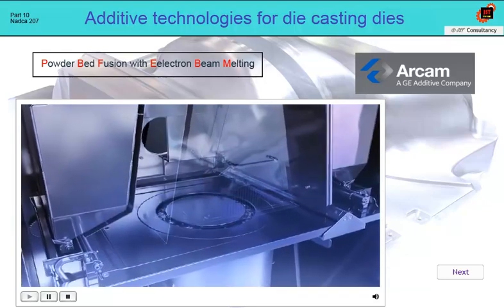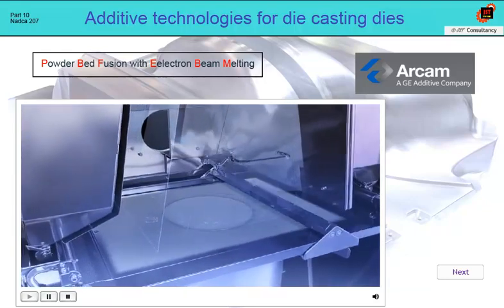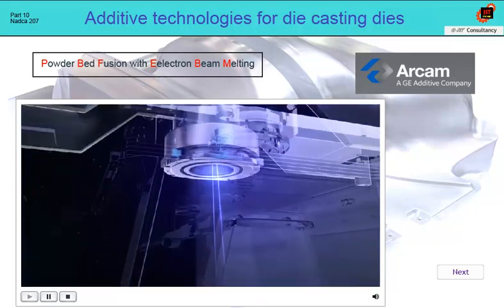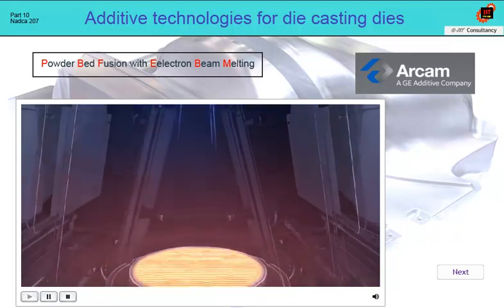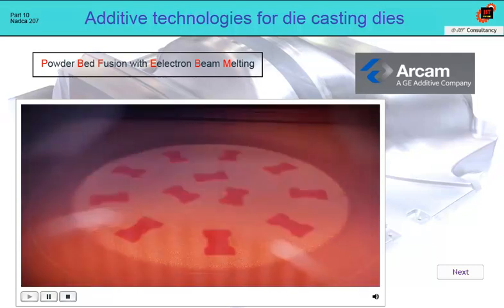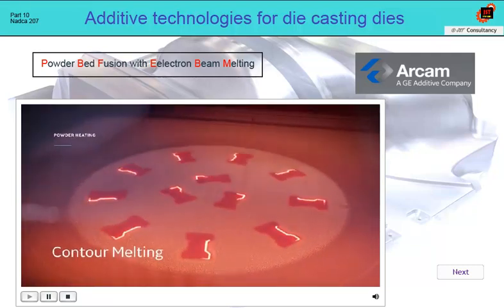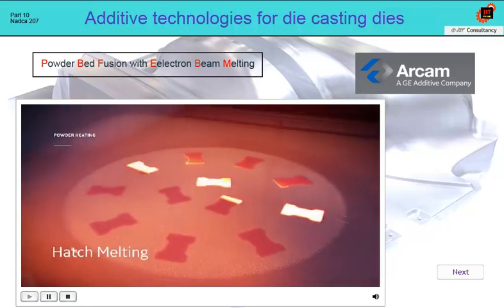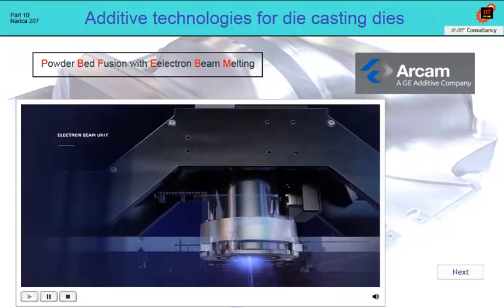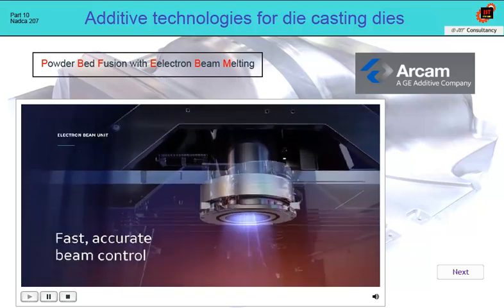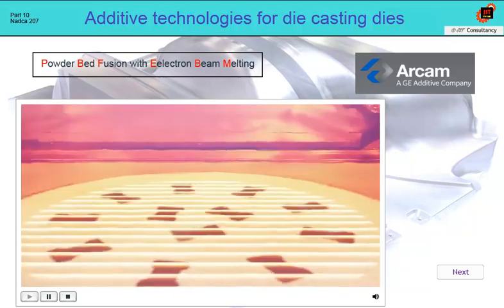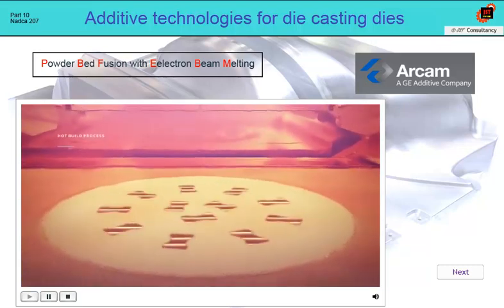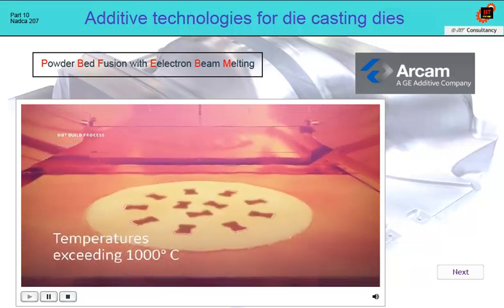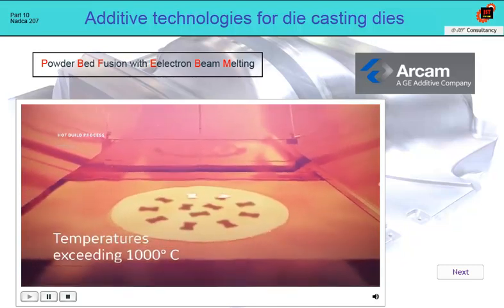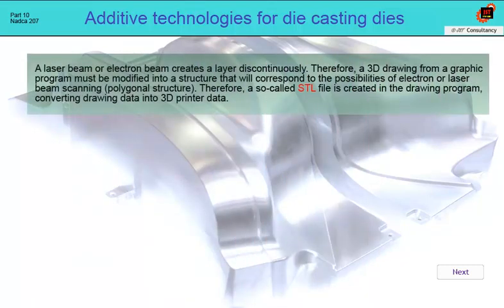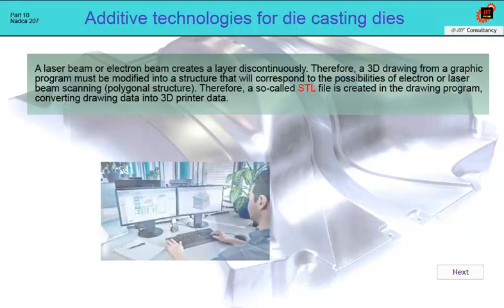Next, Arcam EBM's powder layering system evenly distributes a thin layer of powder on the build area. A powerful 6 kilowatt electron beam heats the powder bed to the optimal ambient temperature and then proceeds to melt the powder, first contour melting and then hatch melting. The electron beam unit generating the beam contains no moving parts, allowing for extremely fast and accurate beam control. The build environment is kept hot, reaching temperatures exceeding 1000 degrees Celsius, resulting in no residual stresses and allowing for the processing of crack-prone materials.